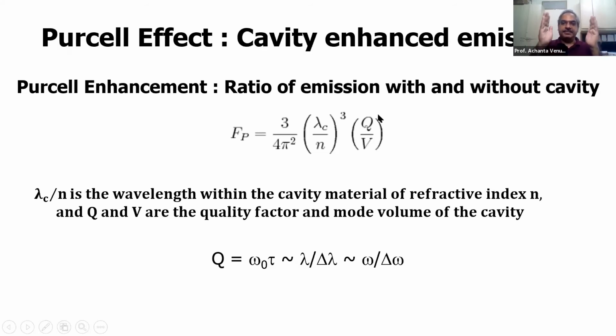Right? And if you have a cavity, you have a quality factor, and also this V, which is the mode volume, right? So you have a certain mode. In terms of easy to understand, if you have a photonic crystal cavity, I said there is a defect mode, a point defect. So the point defect is going to have a local electric field at that position that has a certain volume. That volume is defined by this V. In some defect modes and some cavity modes, you may have a large volume. If you have a larger mode volume, your Purcell enhancement is going to be smaller, right? You should have large Q and small V to get high Purcell enhancement, right?